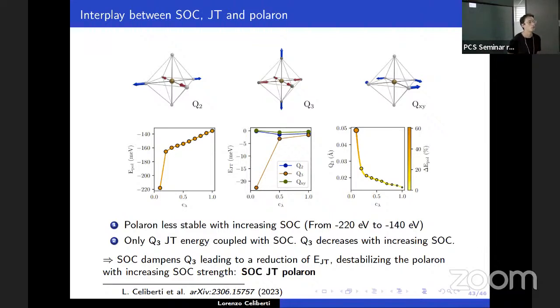Also, I have a question too. Is there any physical reason why the Q3 has lowest energy in the absence of spin-orbital coupling? I mean, in the presence of spin-orbital coupling, the three are most comparable with each other, but only Q3 has the lowest energy. So it should be related to the structure of the orbitals. You have the T2g orbitals, and when you do a tetragonal distortion, you have this orbital that goes down and you gain energy. And it should be related to that. This must be something that the Q3 tries to mix the orbitals that SOC does not want to mix, or something like this. They are kind of orthogonal. So SOC wants also to mix orbitals, but not those that Q3 wants.